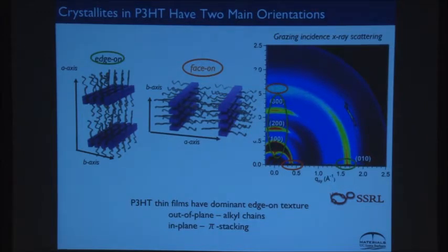So the crystallites that are edge-on, you see more diffraction peaks and more intense diffraction peaks. So of the material that's crystalline, the crystallites that are oriented this way are a little bit more ordered. Okay? But what I have is two populations, and you see that right away from images like this. So that's in a pure material. That's typically what you see.